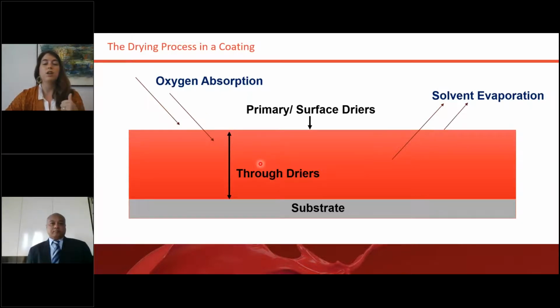So you do need to utilize through-dryers like zirconium. Zirconium carboxylates cross-link hydroxyl and carboxyl functionalities on these alkyd resins. So you get your surface dry and your through dry utilizing two different dryer technologies.